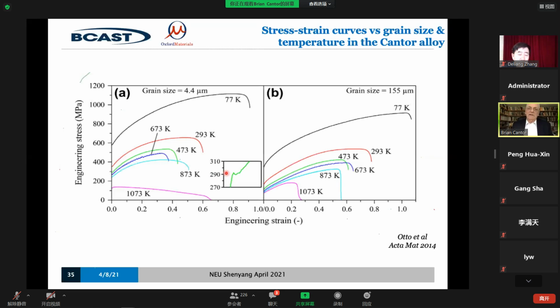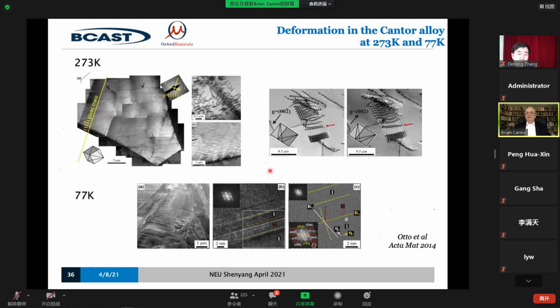And how does it deform? Well, it deforms by simple dislocation pileup. You get what's called planar slip. These are individual dislocations which slip on a single plane and they pile up, which creates barriers, and then you nucleate slip on other planes, and so you get these pile-up barriers here, and that's how the deformation takes place. This is exactly the same as you would see in pure copper or pure gold. There is an important difference, which I'll show you in a second. At low temperatures, you get an additional mode of deformation, which is more common than it is in most FCC materials. You get twinning, which is easier. And that's quite important because it gives extra deformation capability.